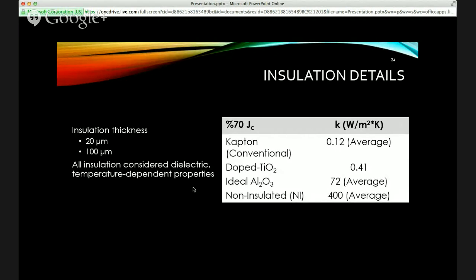And then I looked at the 70% JC. I looked at Kapton, which is the conventional one. You can see its thermal conductivity, as well as doped titanium, which this material is actually developed based upon my master's thesis work. Once I finished my master's thesis, that information was used to submit an SBIR. Then my research group worked with the company to actually develop this material. And then from there, I went back and put that information back into my doctoral work. So it kind of came full circle.